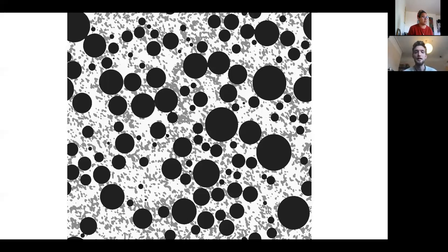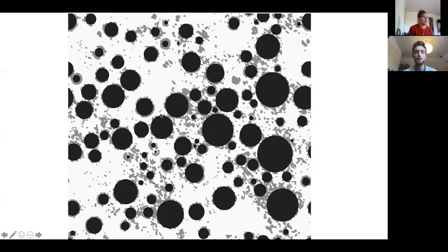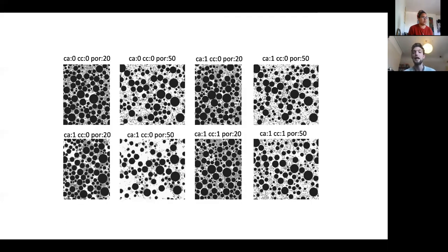So if you can see that we took extreme cases here, so like the max and the min, and we're right now in the process of looking at taking cases in between. So say 35% porosity, where we've trained on 20 and 50. And doing comparisons, so all of the comparisons that we would normally do, and say how realistic does our interpolation look compared to experiment. But there is a fundamental issue here of how we control that interpolation, because there's no real direct way of conditioning your GANs to understand how to interpolate. So that is a challenge.